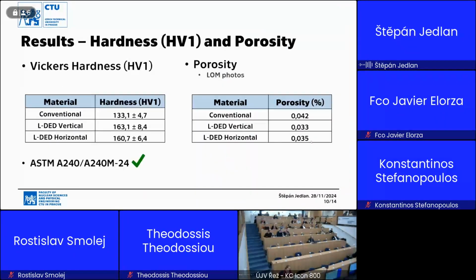Now for the results that we obtained for the hardness and porosity before irradiation, as a result of the chosen heat treatment, you can see that the vertical and horizontal 3D printed samples have almost the same hardness, and this hardness is a little bit bigger than the conventional material has. And for the porosity, we are able to get under 0.1%, which is a very good result. There are a few European projects that have 0.1% as a limit for the porosity, so we were also able to fulfill this limit.